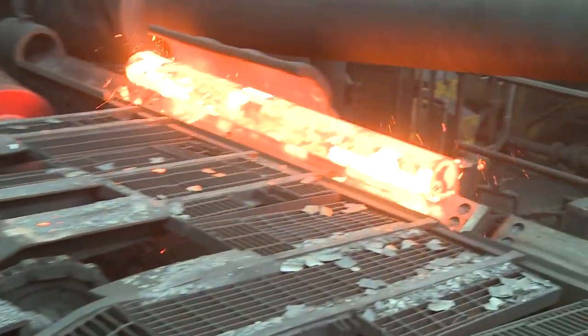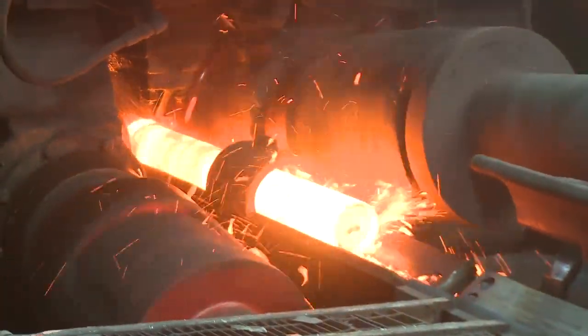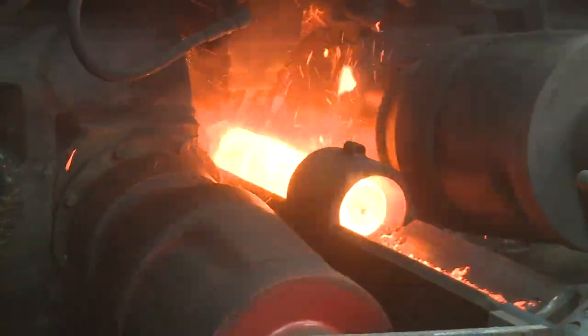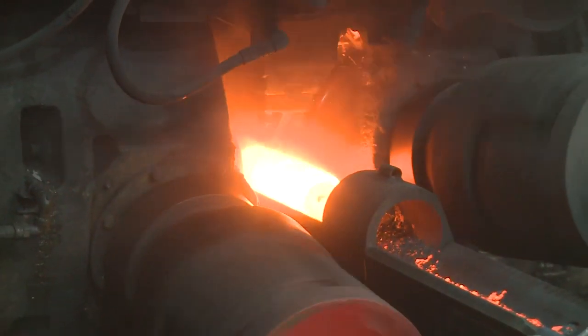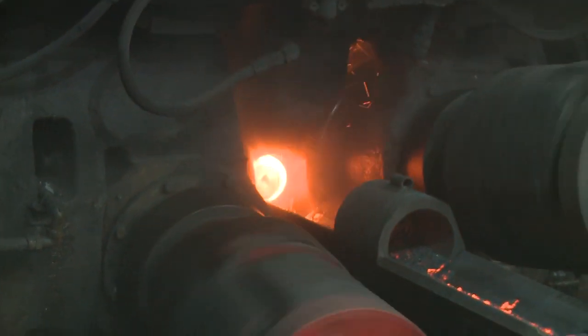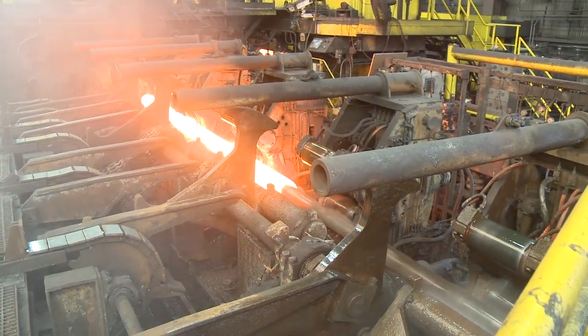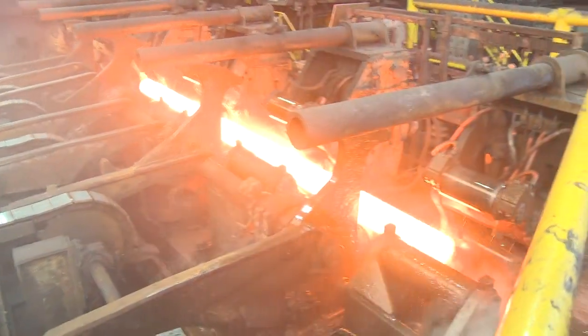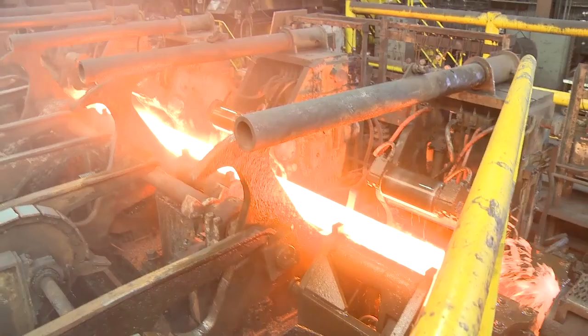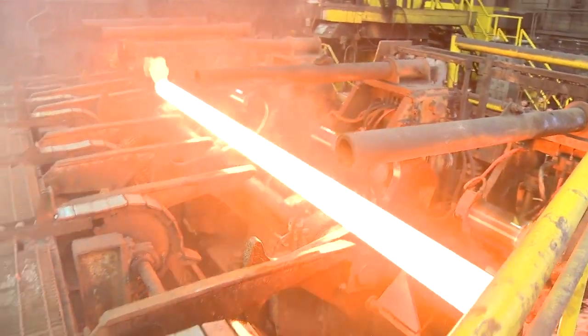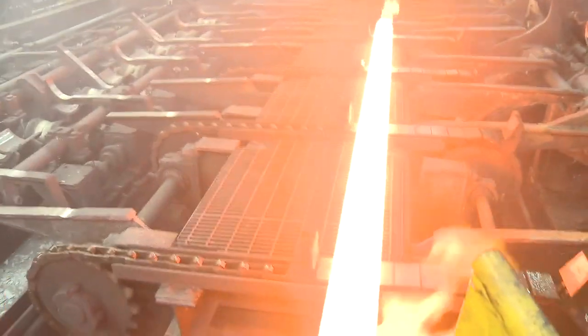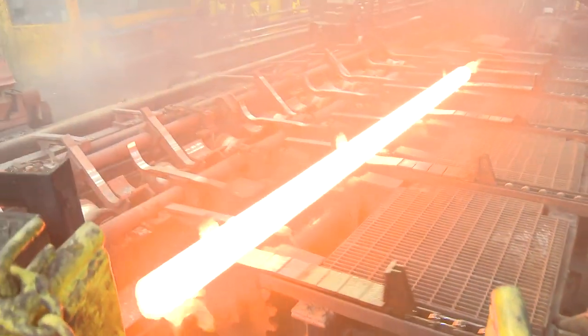The piercing mill uses 2 barrel-shaped rolls, each driven by a motor with 3,000 horsepower capacity, to rotate the billet and force it over the piercing mill plug. A mandrel bar and bar steadiers hold this plug in place to achieve precise concentricity of the wall and outer diameter off of the piercing mill. The hollow tube formed off the piercing mill is now known as a pierced shell.